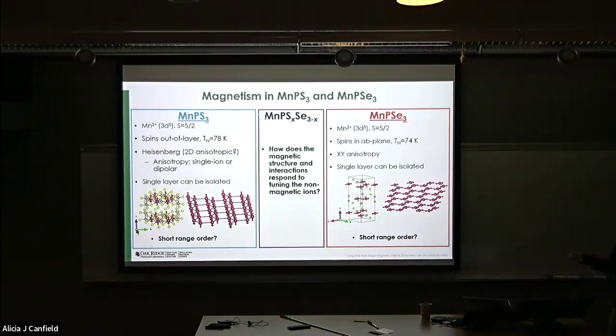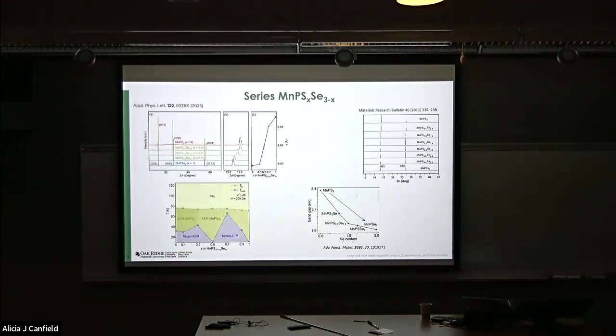Okay, so now I'm going to move on to talk about, well, you have these similar layers of manganese ions, but different magnetic ordering, different space groups. So what happens if you tune between these materials, and really, can you even tune between these materials? There has been some recent work where the series MnPSxSe3-x was synthesized, and you can see that you get a fairly nice series between S3 and Se3 as you tune the ions. There was a phase diagram proposed based on bulk techniques where the transition temperature really doesn't change very much as you tune the non-magnetic ions, but you maybe start to get some interesting magnetic phases at low temperature. And you can tune the band gap as well as you go.